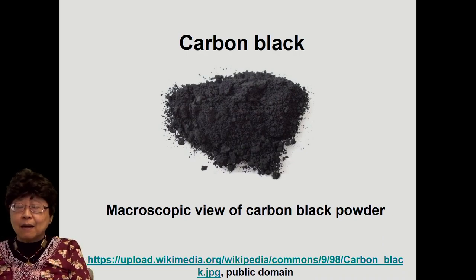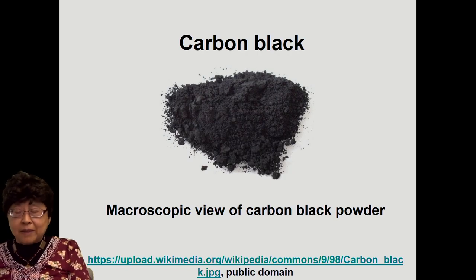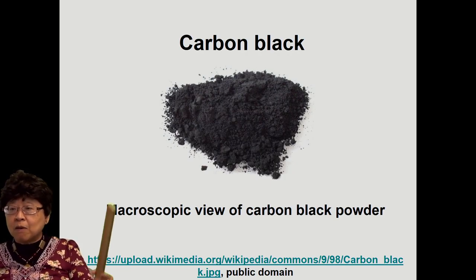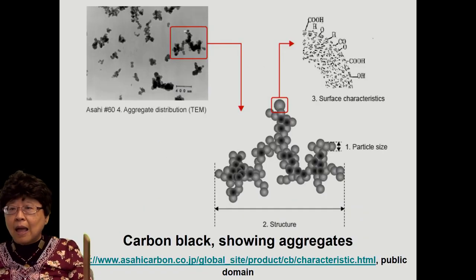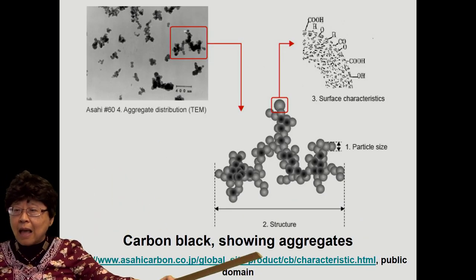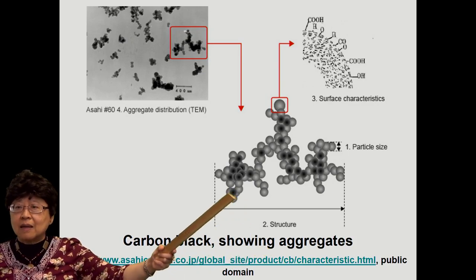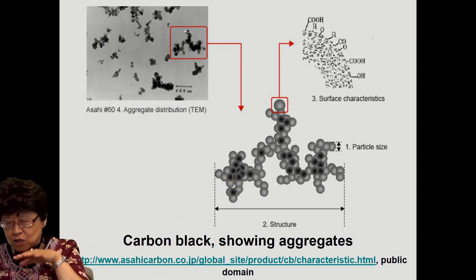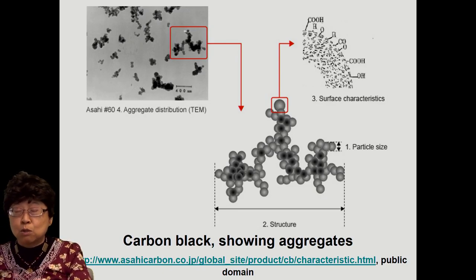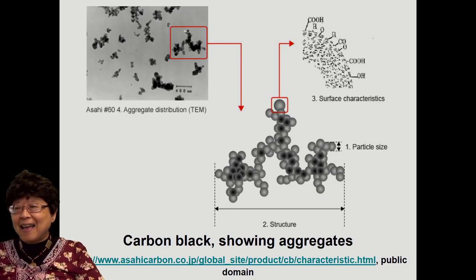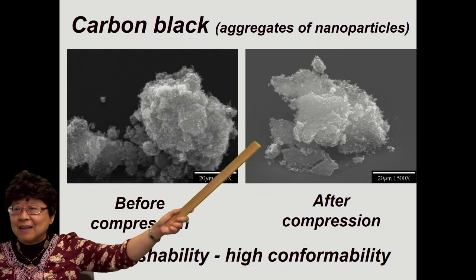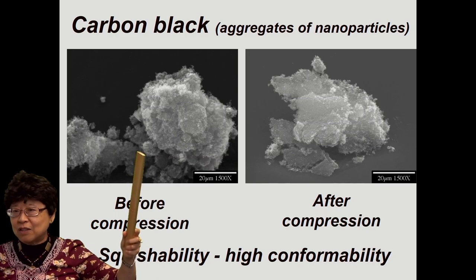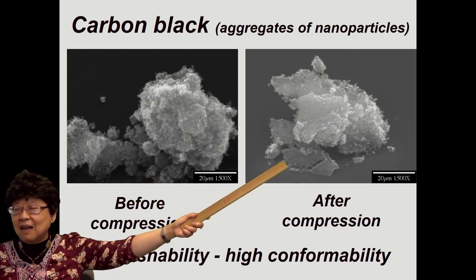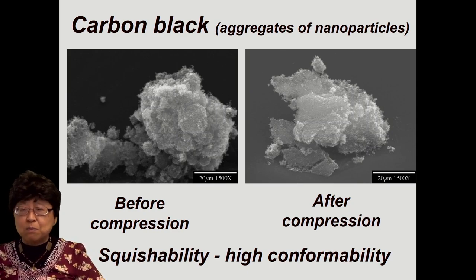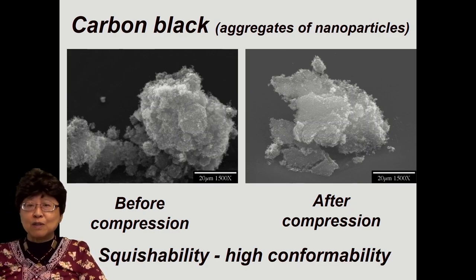Now, carbon black is a form of carbon in the graphite family. That's in the form of powder particles, and it's actually aggregates of nanoparticles. Okay? You can see aggregates of nanoparticles. And because of this morphology, if you just compress it a little bit, it would just squish, and because of that squishing, it becomes conformable. This is before the compression, before the squishing, this is after the squishing. And so after the squishing, it just conforms to the surface topography of whatever surface you use to squish it